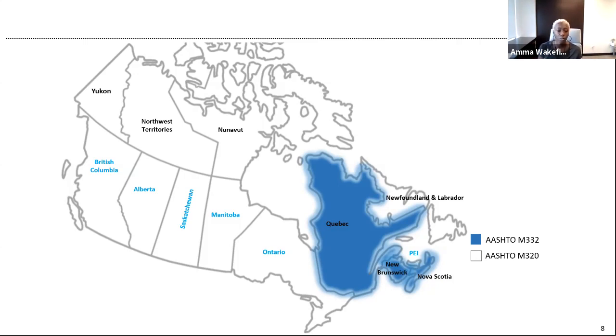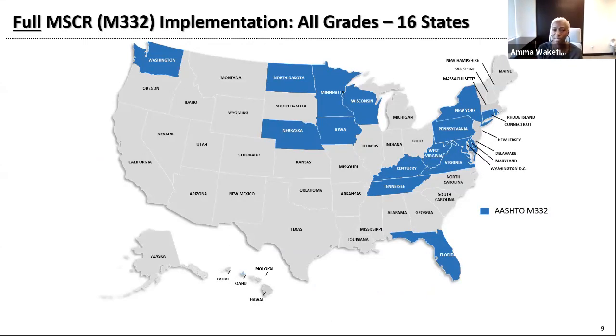Some agencies do this while they're transitioning to the AASHTO M332, just so that it's easier for industry to make that transition. It's not one clean kind of ripping off the Band-Aid effect. That's not necessarily the approach to go with when you're changing specifications related to infrastructure and asphalt binder. So they're using the MSCR test when they feel a need to, and we'll keep track to see if this map changes as we go ahead, to see if they are going to be fully implementing the MSCR specification.